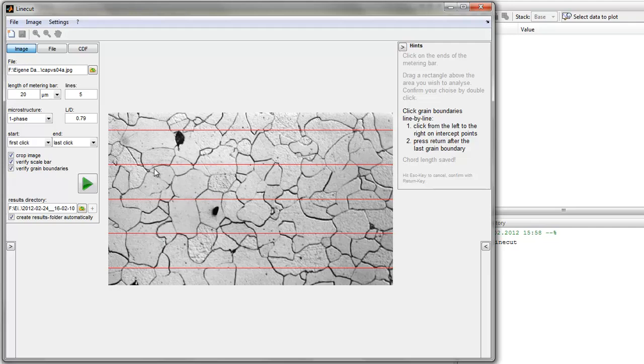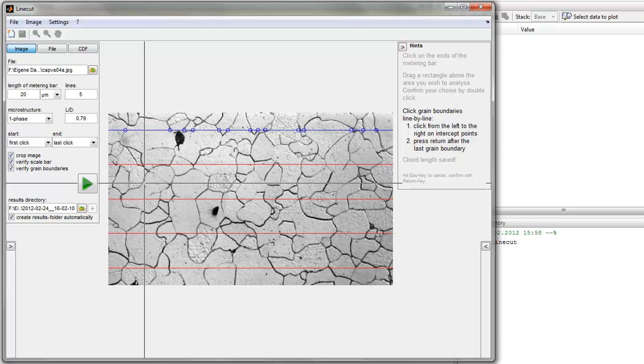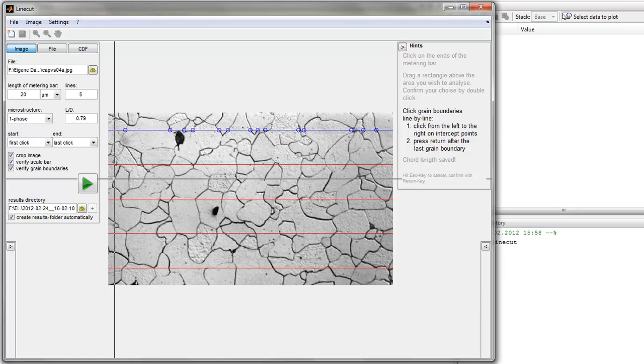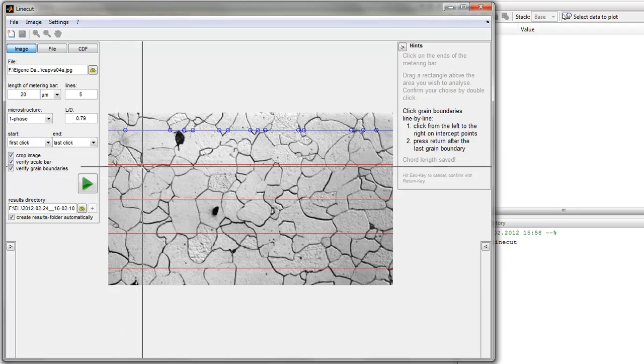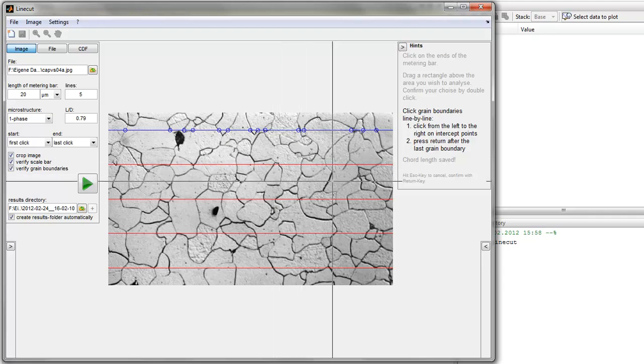You see five red lines on top of the picture, and then you only have to click on the grain boundaries. After each line you have to hit return. Then you will see blue dots where you have clicked. You can check whether it's okay and hit 'yes' for the next line or just hit the return key on your keyboard. It is not important that you precisely hit the line with the crosshair — only the x-coordinate is counted for the analysis. So you can click here or above the line and it will be okay too. You just need to check whether the x-coordinate of the crosshair hits the grain boundary.